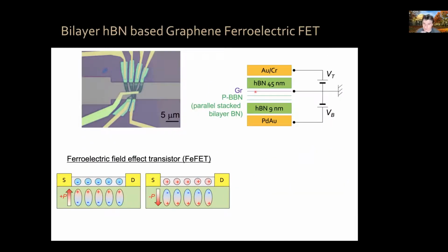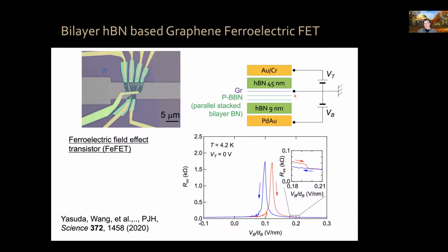And indeed, this is something that you can do. So we have fabricated parallel stack bilayer hexagonal boron nitride. We place graphene on top because in order to investigate the ferroelectric state of the boron nitride, we're going to build a ferroelectric field effect transistor, where the configuration of the parallel stack boron nitride, the electric dipole moment, will lead to a change in the type of carriers in the graphene, and we will see that in the resistivity of graphene. And indeed, if you make this type of devices and measure the resistivity as a function of electric field, you see that you obtain hysteresis when you sweep up and when you sweep down as a function of electric field. And this hysteresis is indicative of this ferroelectric behavior.